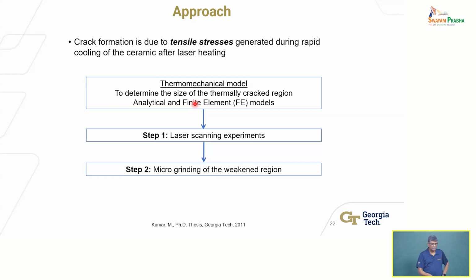And then once we have determined the size of the thermally cracked region for given laser parameters, or the other way around, the size, because you're going to produce that feature. So given the size, what should my laser power be? What should my energy distribution be, such that I generate thermal stresses that exceed the fracture strength of the material? That is the objective. You can answer that question using the model, and then you do this laser scanning process, right? And then once you've done that, you try micro grinding. In this case, we did micro grinding. We are trying to produce micro scale features in the weakened region and see what happens, right?